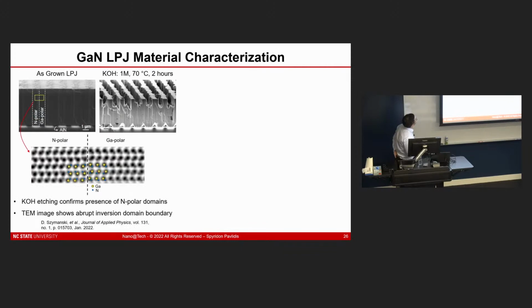So we are doing two things, right? Through the initial patterning of that aluminum nitride template, we are controlling how the growth will initiate and what polarity the GaN will have as it grows vertically from there. So we can control it so that it's gallium polar or nitrogen polar based on whether or not that aluminum nitride template is there. And then those grow side by side.